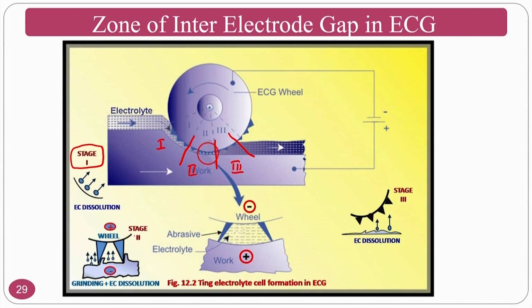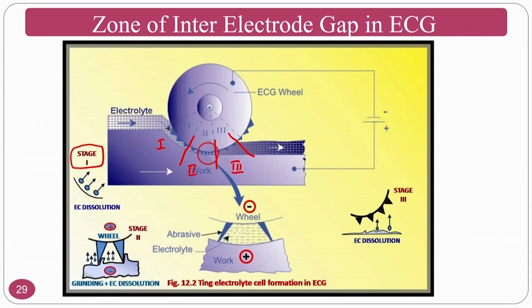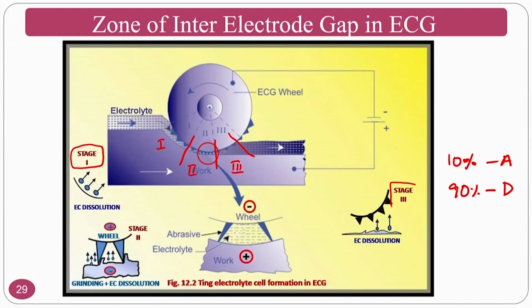In stage 1 it is completely electrolytic dissolution, because of which the metal hydroxides will be formed and material removal will take place. In stage 2, dissolution will be taking place along with the abrasion action. In stage 3 again it will be an electrochemical dissolution process. That is why 10% will be abrasion and 90% will be electrochemical dissolution. That is why the grinding wheel life will be enhanced greatly. Depending on these 3 stages, I will explain how the material removal process takes place.